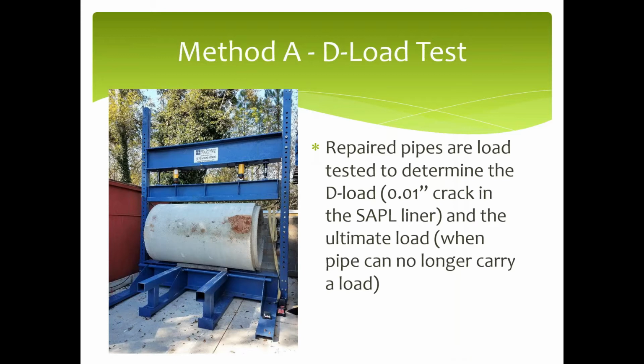And the important thing, the deload this time for the 0.01 crack is going to be in the liner itself. It's not going to be in the pipe anymore because the liner is now carrying that load. And once we get to that, we're going to continue loading until we get to the ultimate load, which again is when that pipe with the liner can no longer carry a load. And we record all that information, and that's what's reported through Datamine.